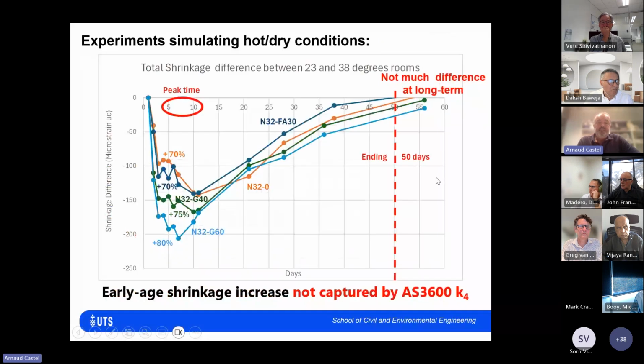So here I'm presenting the difference, which is shrinkage at 38 degrees minus shrinkage at 23 degrees. I'm just talking about that 32 MPa concrete today, and there are 4 of them. The 0 is always no SCM. Then there's 30% fly ash, 60% slag, and 40% slag. The difference here is in microstrain, but I also added the increase in percentage between the shrinkages measured at the two conditions. So what we can see is that regardless of the binder composition, the peak time, when the difference is maximum, is between 5 and 10 days, which is within the range of early age cracking time.